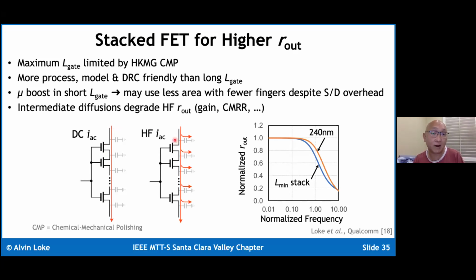To an RF crowd, this is obviously important. At some frequency, these intermediate capacitances start to shunt away AC current, which means that if you were to compare, say, an Lmax device of 240 nanometers versus a stack of Lmin devices, which achieves the same normalized Rout, you can see that the Rout basically starts to deteriorate at about 15-20% lower normalized frequency, simply because as AC current starts to shunt away through these parasitic capacitances and not go all the way through the transistor stack, then effectively it's going through a shorter channel length and therefore worse Rout.